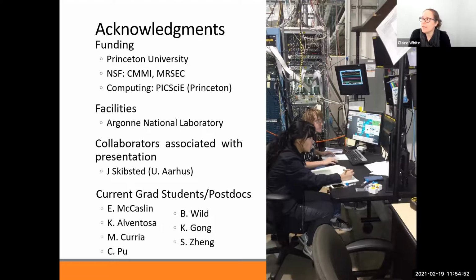So one thing that we are doing more nowadays is comparing DFT structures and force field based structures to experimental data to try and better interpret the atom-atom correlations, especially past about 4 angstroms, because up to about 4 angstroms, you can get a sense from knowing the chemistry and the other experimental data, you can help to interpret that. But beyond that, it becomes a lot harder. Yeah. We're moving towards structural models to help interpret that. Okay, great. Thank you.